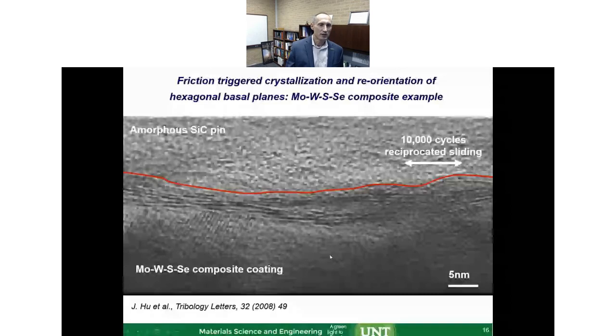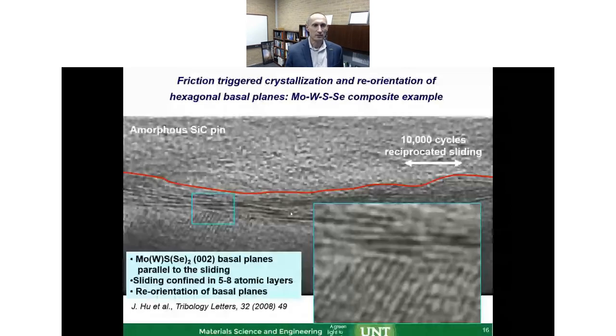And after that, there's pretty much no wear because of the reorientation of the randomly oriented grains, and the amorphous grains turned into the crystalline hexagonal phase in here. And this is the adaptive mechanism for that chameleon solid, which is well known. And this here is the confirmation of how you can see it in real life. All right, but let me move in here to some demonstration of how this gets used.